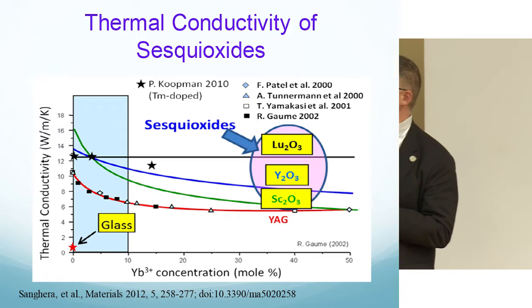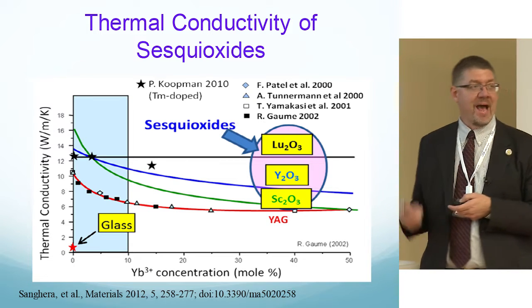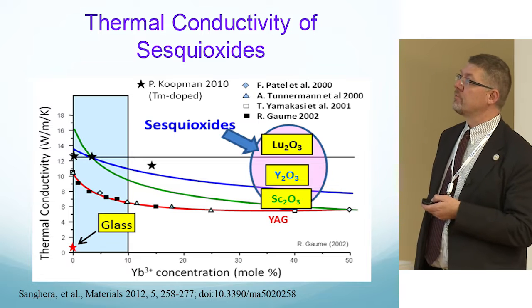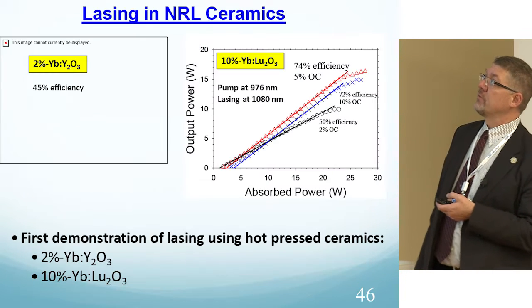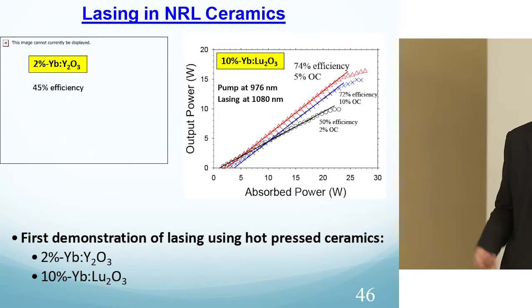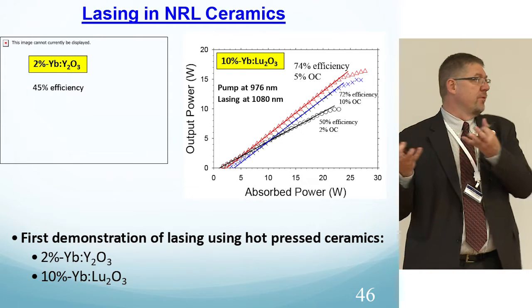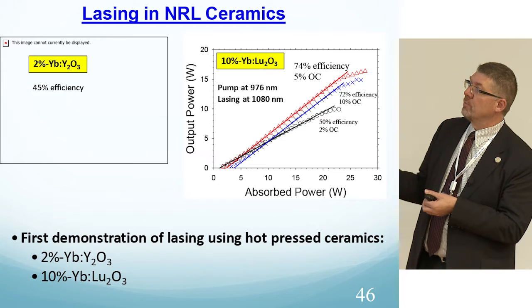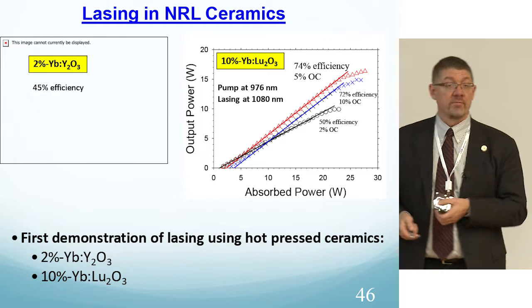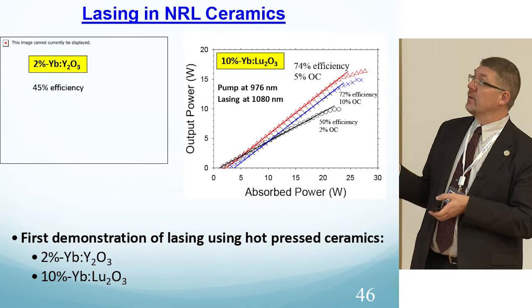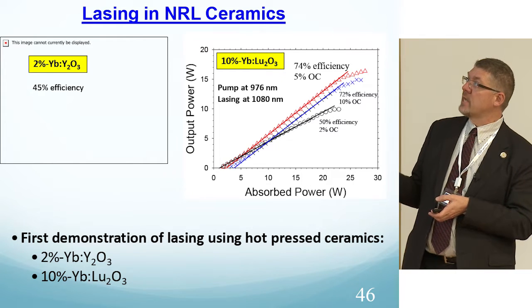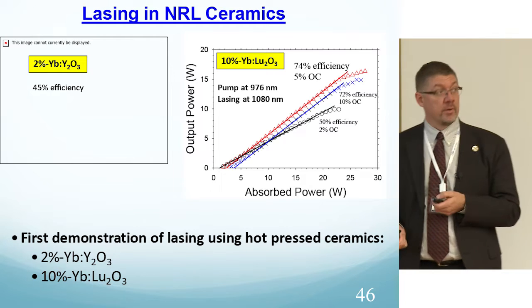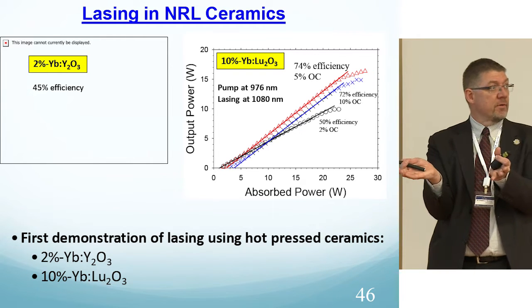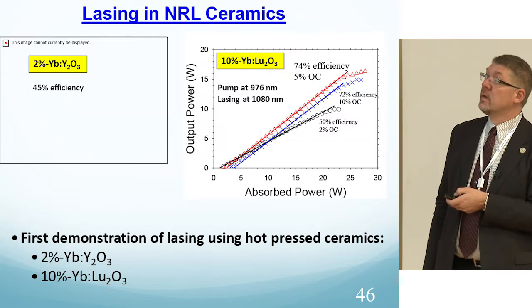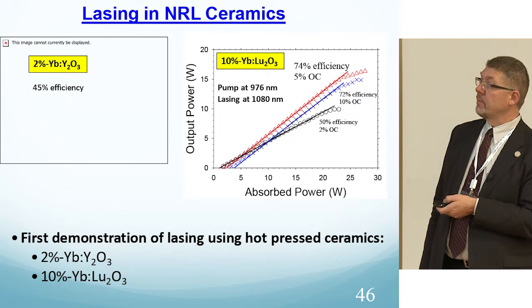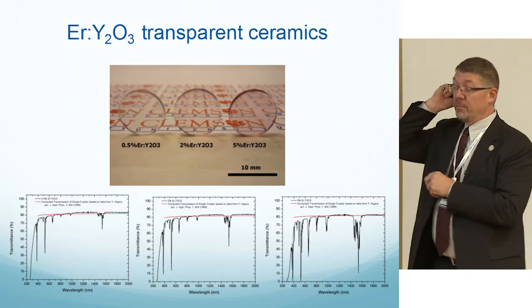So there's been a large drive in the last 5 years to really understand how to manufacture these type of materials in ceramic processing. And the other nice thing is they're very efficient. As we showed previously with the quantum defect, for ytterbium in a standard host, 80% is the maximum efficiency. And this group at NRL has shown 74% efficiency with their ytterbium-based materials. So they're getting something on the order of 18 watts out for 25 watts in, and that's a pretty good exchange from going from a very broad, highly divergent diode beam to a very nicely confined laser beam at 1080 nanometers.